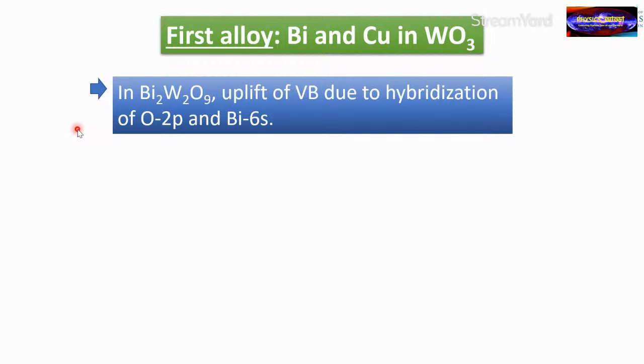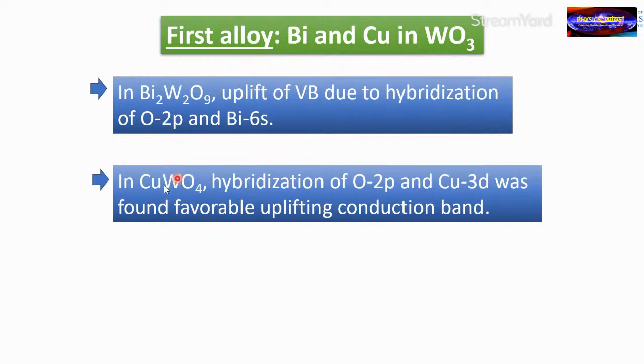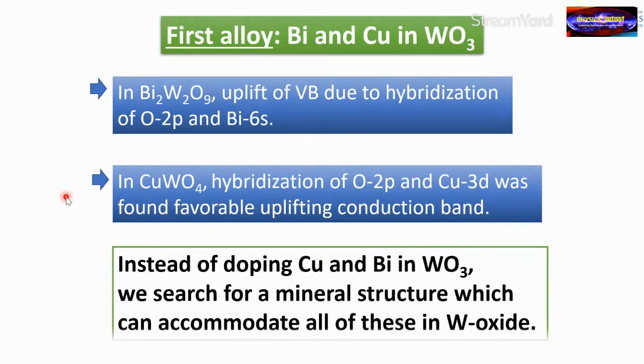You can search the word in Google. And then why copper? Because we found in copper tungstate, the hybridization or coupling of oxygen 2p and copper 3d also makes a favorable conduction band uplift and increases the pd transition, which is a favorable transition. Hence, you can see in both cases, whether we put bismuth or copper, oxygen 2p plays an important role. How did we determine bismuth and copper? Instead of doping copper and bismuth, we search for a new structure that can accommodate them in tungsten.